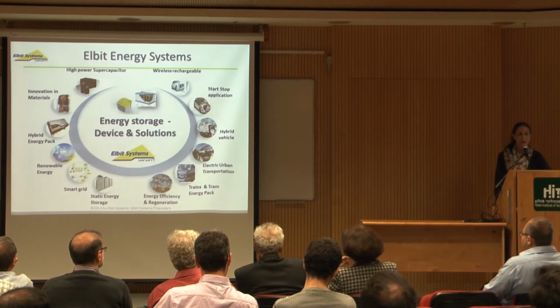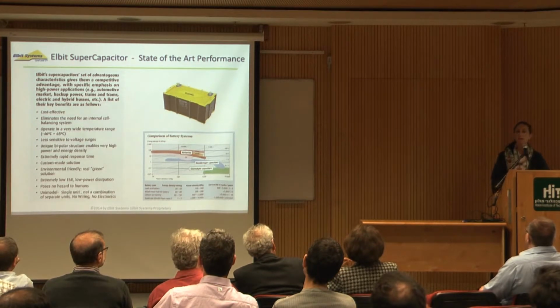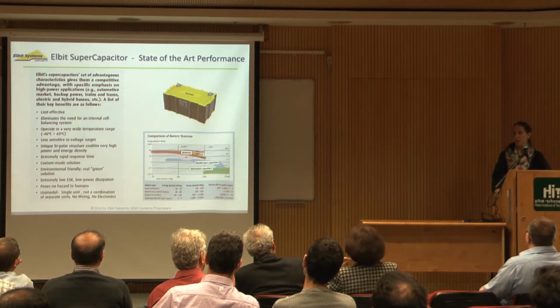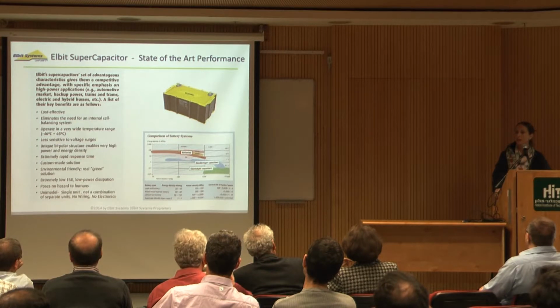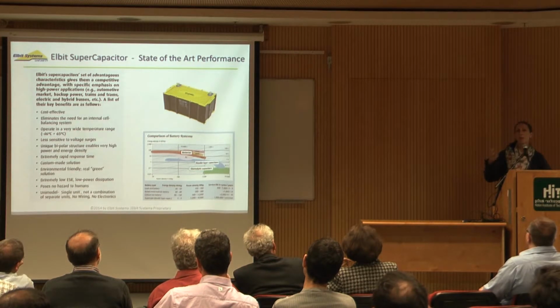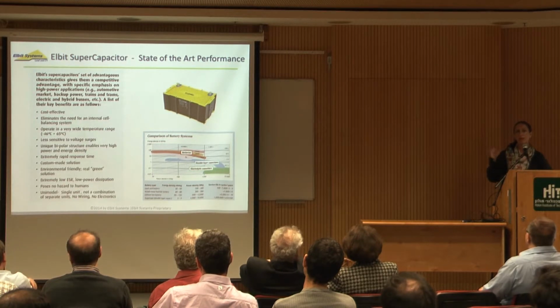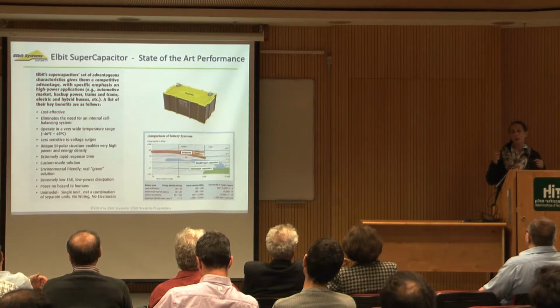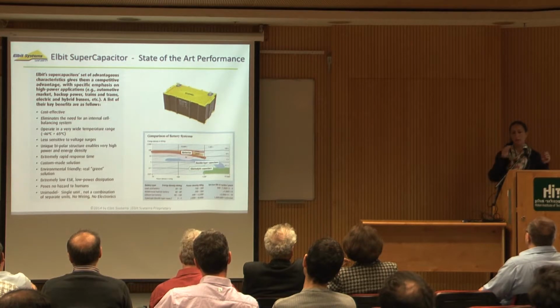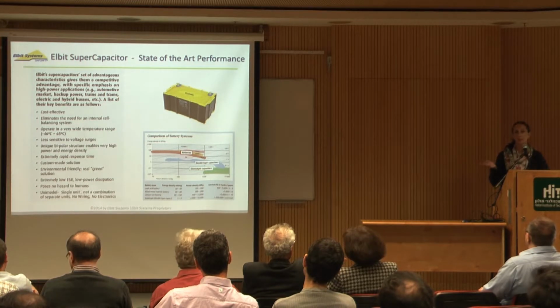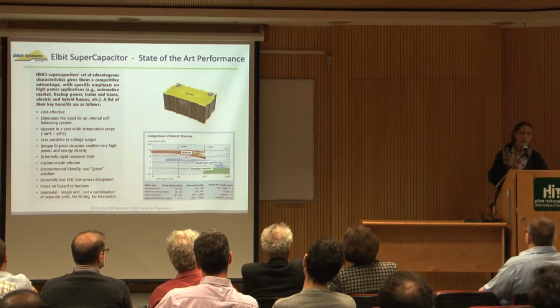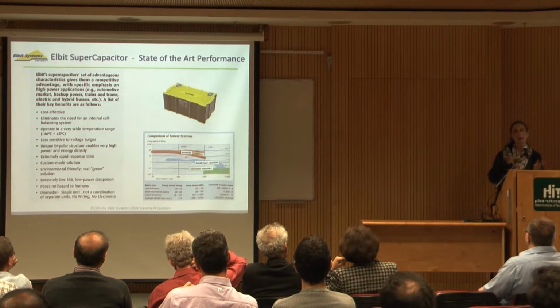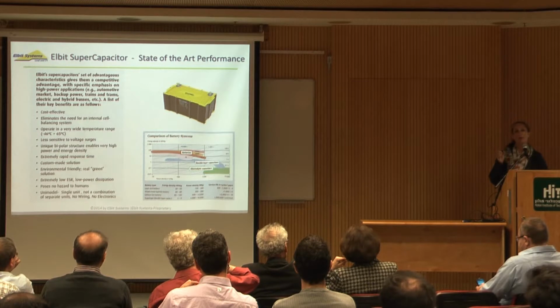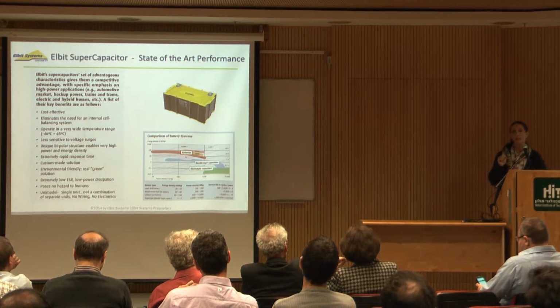stability. But actually, this is one of the strong points of this solution in comparison to the commercial organic supercapacitors, which suffer at temperatures beyond -20, -30, and in order to overcome that limit, they usually implement, in terms of the design, thermal insulation, so that they will not be so sensitive to the temperature. And this is one of the strong points of this kind of supercapacitor, because of this aqueous electrolyte and also the bipolar stack configuration, which gives a very low ESR, which is also less sensitive to temperatures.